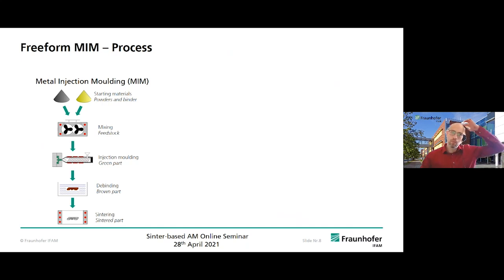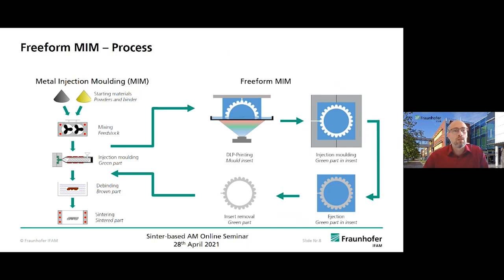Next, I want to go to the freeform metal injection molding process. I guess this is less known than the FFF. The MIM process, as probably many of you will know, starts with making a feedstock by combining powder and binder, mixing it into this feedstock, and then injection molding the part into a green part form, and then having the debinding and sintering. And the freeform MIM basically comes in before you make the green part, because what you do additionally is that you print a part, in this case by making use of direct light processing. So it's a lithography based printing of a polymer part with a very special kind of resin.